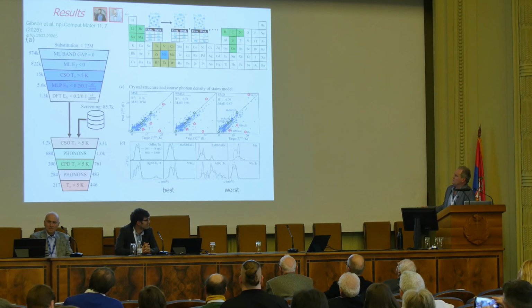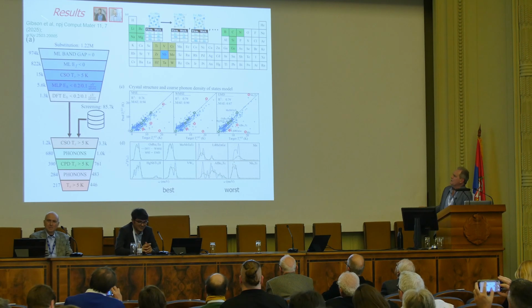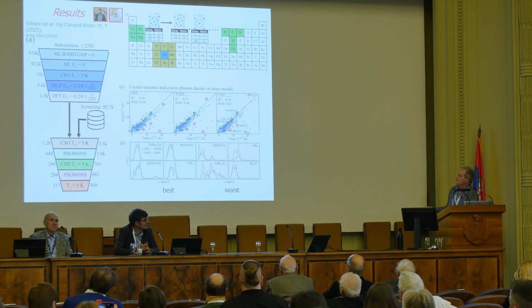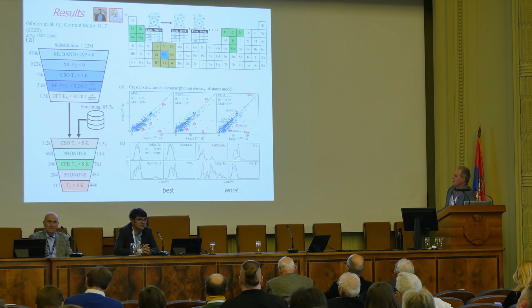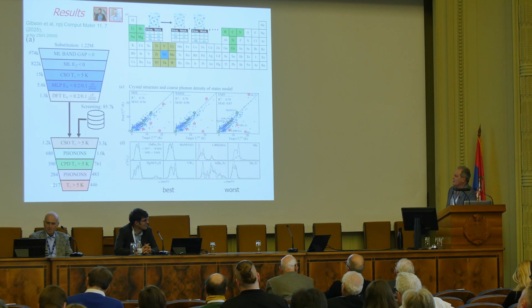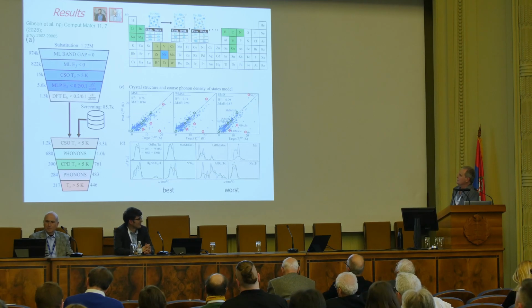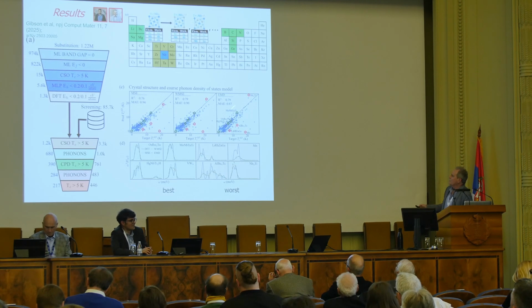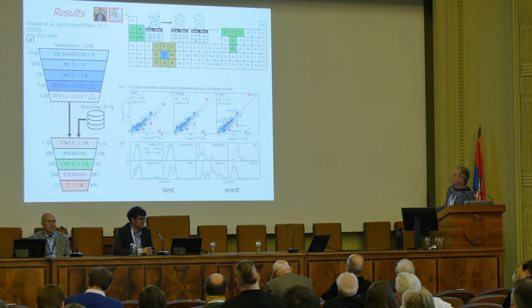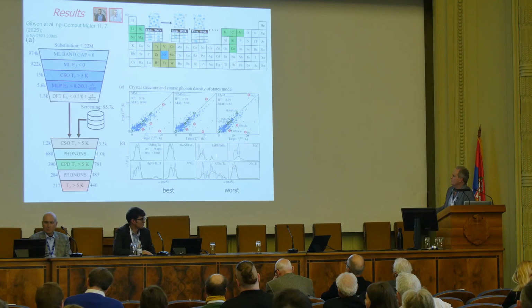We start with a database of materials, crystal structures, I should say. This is the so-called Alexandria database. And we screen them down, one criterion after another. Are the phonons stable? Are the systems thermodynamically stable, i.e. close to the convex hull? Is the predicted TC greater than 5 Kelvin? And then we plot what we get. There are some outliers. These are the worst cases down here that we do very poorly on.